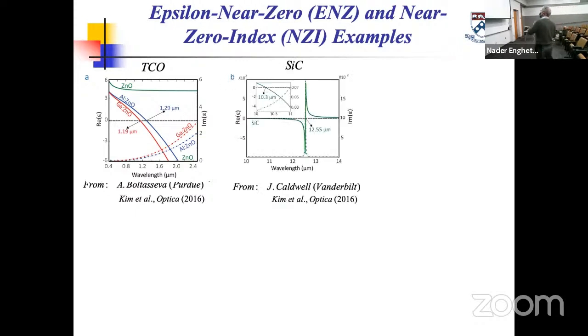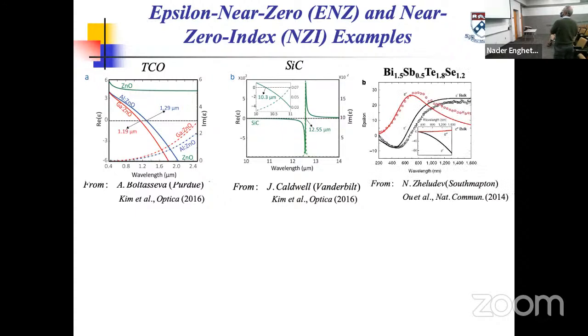But if you go to mid-IR, things even better. Silicon carbide at around 10.3 micron had the real part of permittivity zero. The imaginary part could be very small, could be 0.03. These are very good material as ENZ material. If you go to the UV regime, my friend Nikolai Zheludev from University of Southampton studied some of the topological insulators, and you notice they become ENZ around 200 nanometer wavelength.